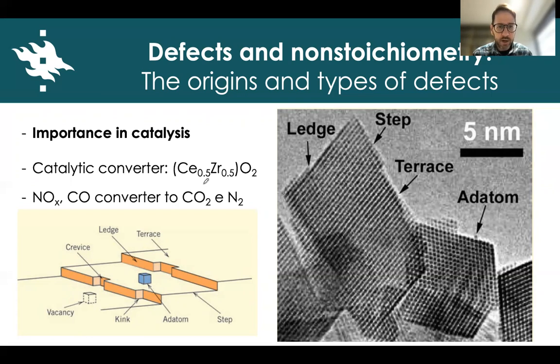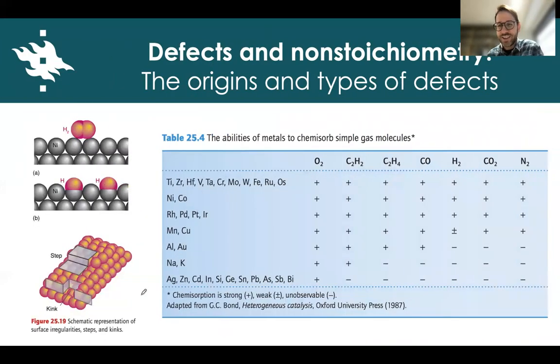For example, here we have a nanoparticle of cerium and zirconium oxide, in which, on the surface of this nanoparticle, we can have different types of surface defects, such as terrace versus ledge versus crevice versus kink sites, or the presence of adatoms and steps. At these defect sites, we already have a lower coordination number at the surface, but then we can have even lower coordination numbers, which means regions of increased energy and therefore increased reactivity. And this leads to increased capacity to act as a catalyst, or gives rise to a catalyst with good performance towards a variety of molecules, because catalysis involves the chemisorption and splitting of molecules at the surface of these solid materials.